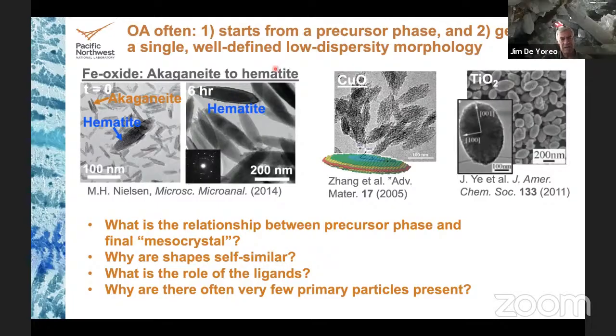And the second is that you'll notice that these particles are all very similar in size and shape. And here are a couple other examples: copper oxide, titanium oxide. These are all so-called mesocrystals. That is, they are made from individual nanocrystals, but they end up diffracting as single crystals. They're all co-aligned particles, but they all have a similar size and shape. And that's not what you would expect for a process in which particles form and diffuse randomly and attach. That ought to give you fractal shapes with a power law distribution of sizes.